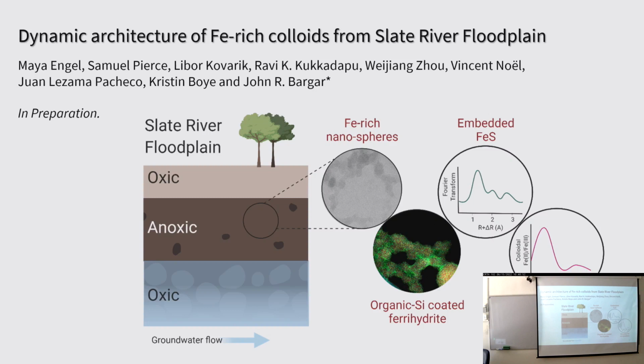So, I don't want to skip. Wait a minute, I can show you some figures afterwards that are not part of the presentation. But what we're seeing is that it appears that in spring we have a lower downward pore water velocity. So it seems that the residence time of the colloids in the anoxic zones is longer. So we're hypothesizing that there's just more time for reactions to take place. I'm not sure exactly about the kinetics, but it's probably a slow process that's taking place. And that's why we see more reduced iron in spring.